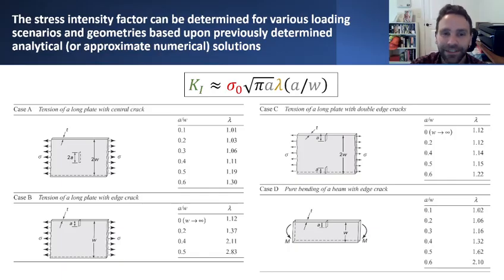Now, that might not necessarily be a satisfying result. In some cases, you might actually want to visualize, well, what is the exact distribution of stress in the local vicinity of the crack tip? And it turns out that as you look closer and closer to the edge of one of these cracks, the solution starts to look basically the same regardless of the particular geometry that you're looking at and regardless of the loading conditions that you're applying to this plate.